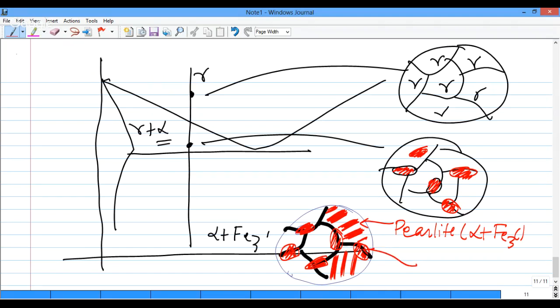And this is alpha which formed before the eutectoid reaction. The eutectoid reaction took place at this horizontal. This alpha had already formed before that reaction. So we call them proeutectoid alpha. To find the fraction, since this proeutectoid alpha formed above the horizontal, you have to draw a tie line in the gamma plus alpha region, just above the eutectoid horizontal. Because you can see proeutectoid alpha was historically forming there, although you are observing it at room temperature, in terms of history, it formed in the gamma plus alpha region.